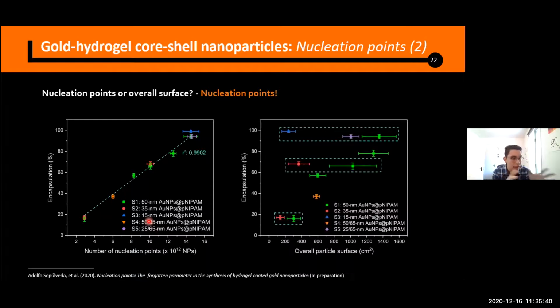And these are the same results, but in terms of the overall particle surface. It is just to prove that for a given number of nucleation points, which leads to a specific encapsulation yield, if we use different particle sizes, having different overall particle surface in the solution, they have the same encapsulation yield. And this is what is happening in these three cases.